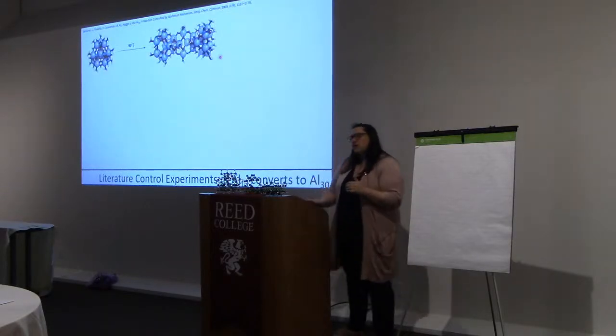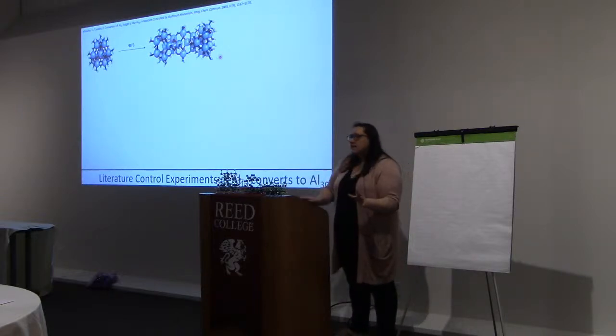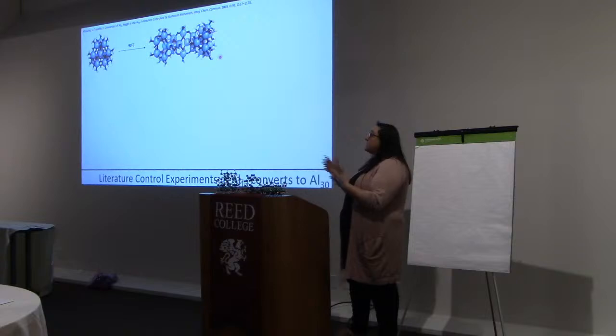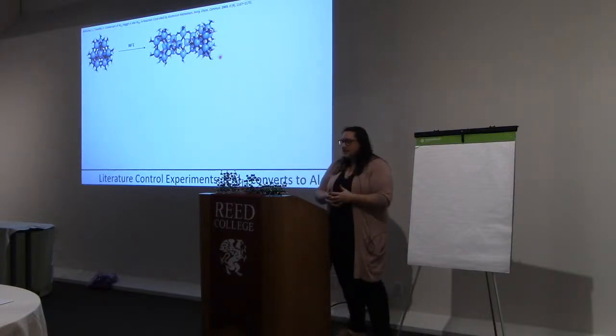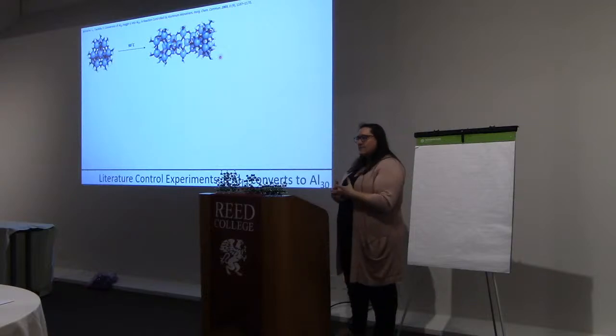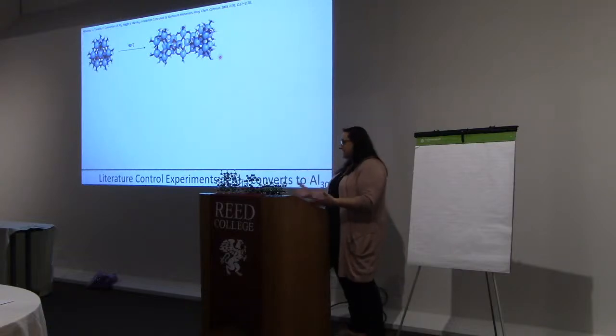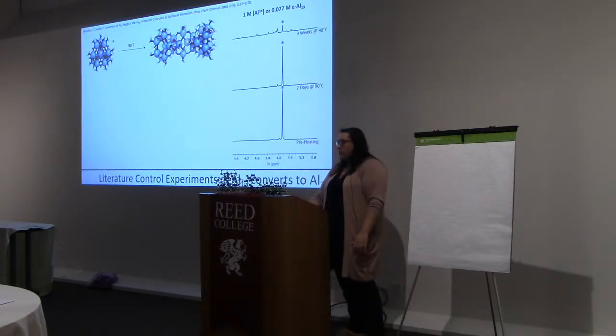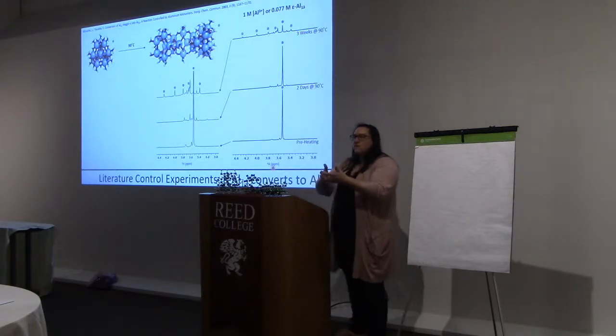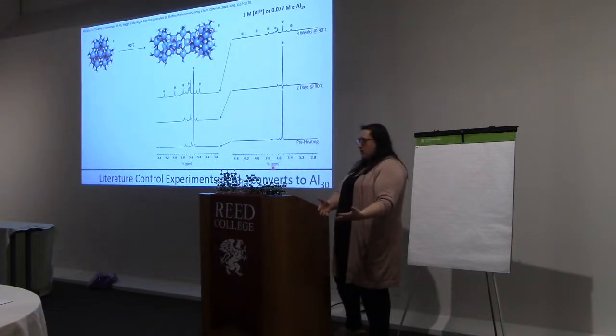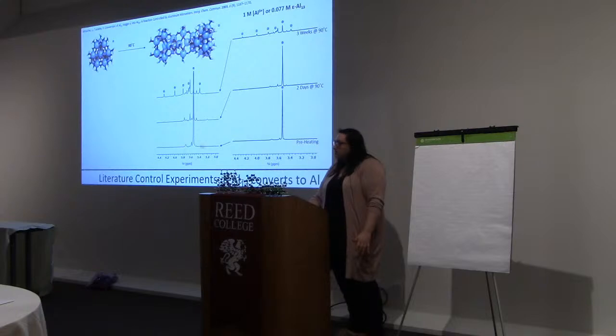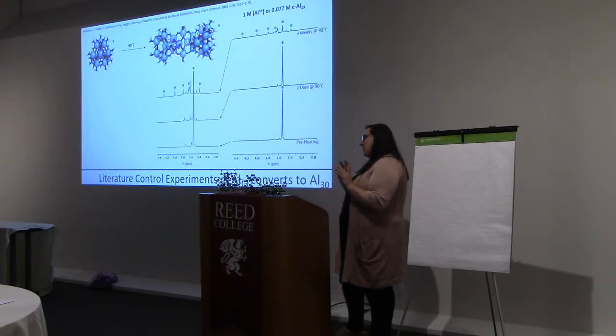The next thing that we wanted to do was go to the literature and mimic an experiment that was happening and see if we could see the same results using proton NMR as they had seen in the literature. And so we know that if we take our epsilon Keggin and we heat it over time, it converts into Al30. And so that's what we wanted to see. Before we heated it, it was just mainly this big signal. And over time, after 3 weeks, more small signals grew in. Now those signals, if we zoom in and look at it, correspond to where those 30 signals were. Now, interestingly, there are some other signals in here that we don't know what they are yet, so I'll talk about that in a moment.